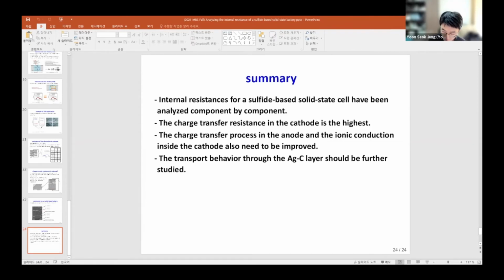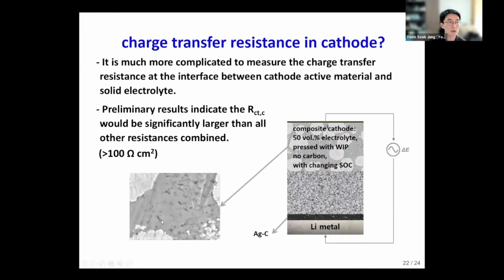Dr. Im, I have several questions. Very systematic and interesting analysis, I think, for deconvoluting every resistance. I think the formation of an interface between the silver carbon layer and lithium metal may not correspond to the real interface in the anode-less cell. So even though you obtain some interfacial resistance for the control system, it may not reflect the real values. How do you think about that issue?